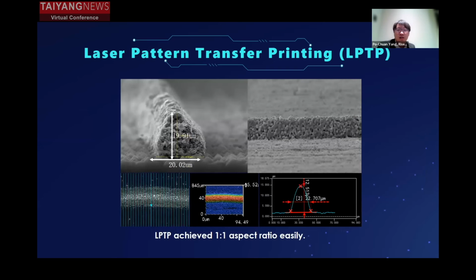compared to the low temperature silver paste. And another kind of candidate to improve the metallization is the laser pattern transfer printing. We fill the groove with paste first, then use laser to transfer the paste on the cell. In this case, we can achieve very good aspect ratio, and there is no damage on cell level since it is a non-contact printing method.